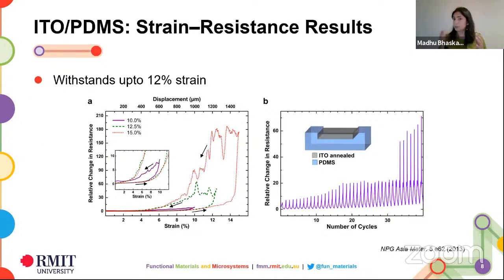So we thought, okay, we managed to transfer the indium tin oxide onto PDMS. Now, generally, indium tin oxide, like any other oxide, is brittle. So it will not withstand anything beyond, say, 3 or 4% of strain. So we strained these to see what exactly happens to the resistance parameters. Surprisingly, it behaved okay up to almost around 12% of strain. And then beyond 15%, it kind of went open circuit.